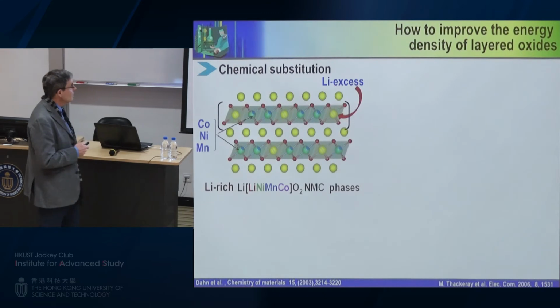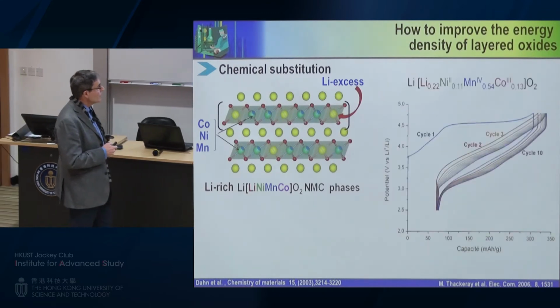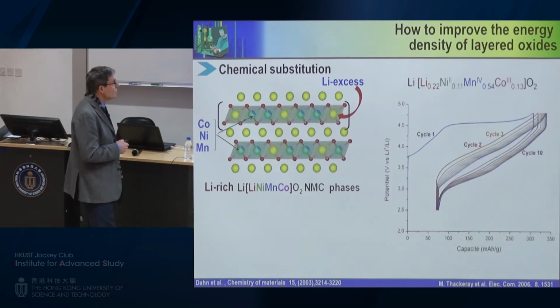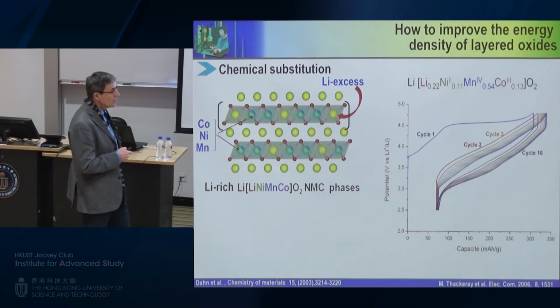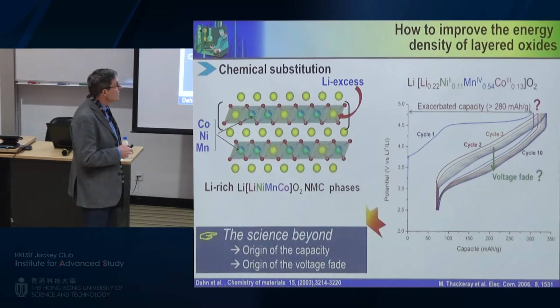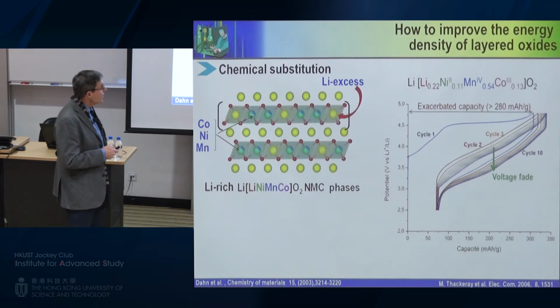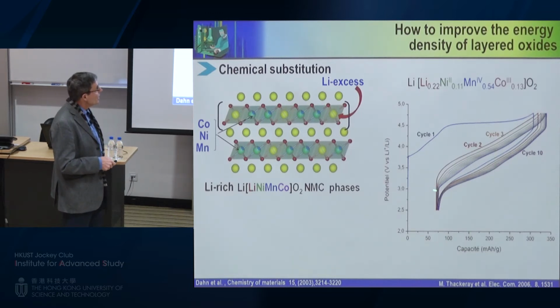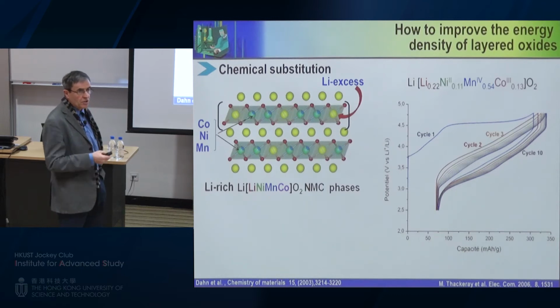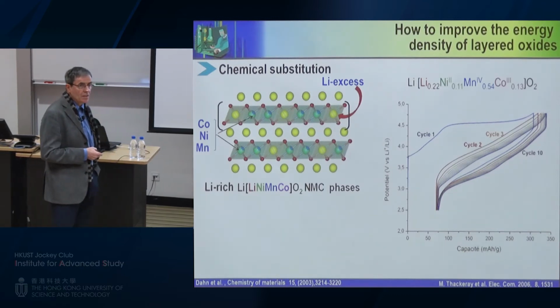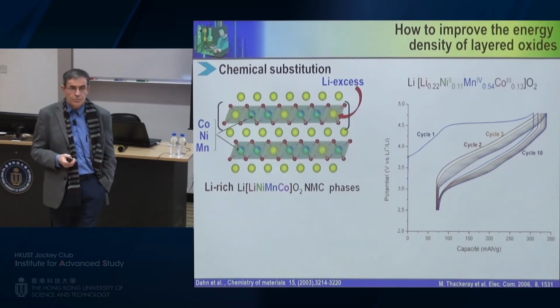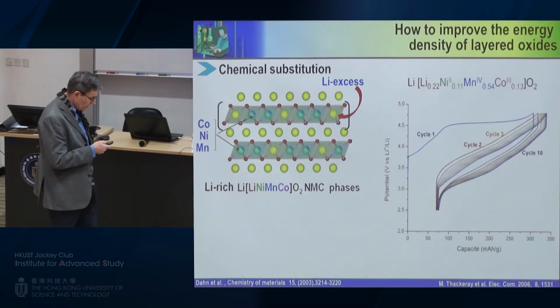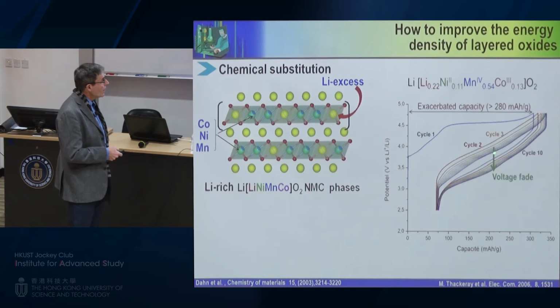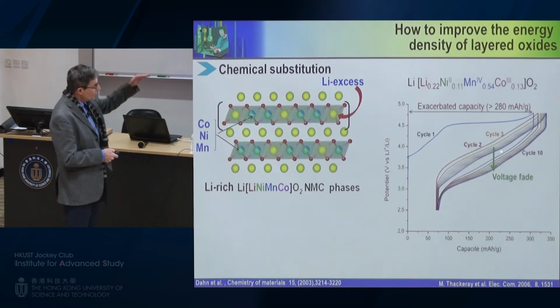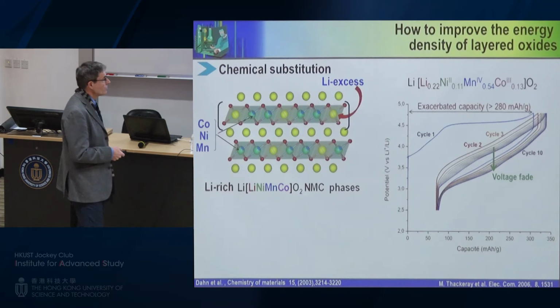When you look at this compound, why are people excited about it? Because I will say you have good news and bad news. The good news is that you can really increase the capacity, since in this case you can see that we have capacity reaching about 250, 270 instead of 190 as you had before. But the bad news is that during cycling, the voltage continuously fades.